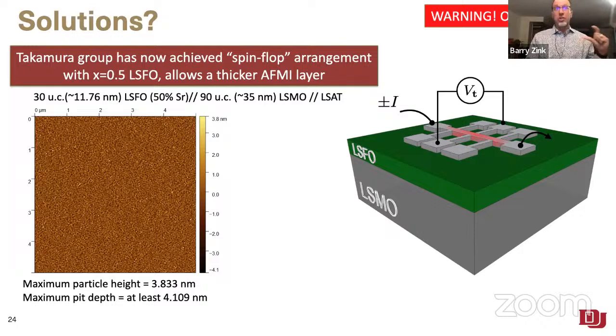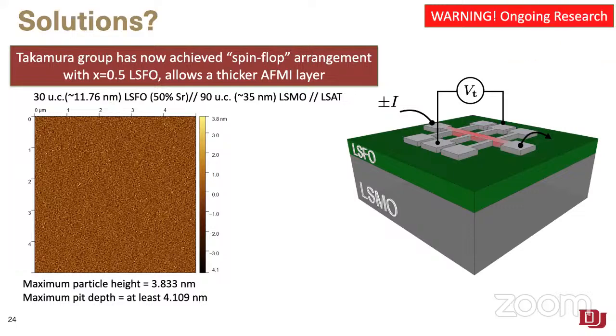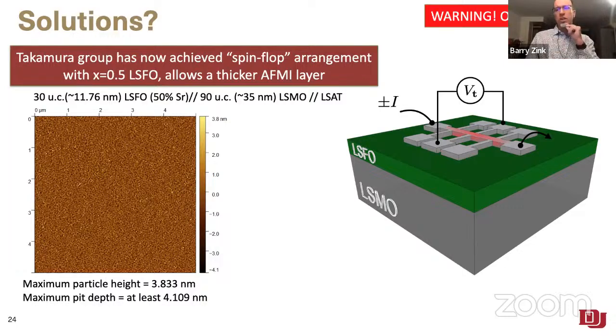Yayoi has been able, with significant work, to get rid of those missing grains and to grow somewhat thicker antiferromagnetic layers, so that we're not at least having the problem of a direct contact between our platinum or whatever material we use and the conducting LSMO beneath. Yeah, this is very close to the end.